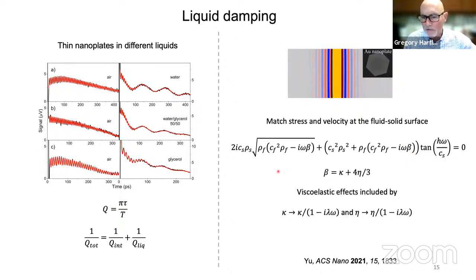Okay, so this equation has the densities of the solid, the densities and speeds of sound of the solid and the liquid. It has the viscosity of the liquid in this beta parameter. So if you leave out viscosity, then you just have the liquid like it was a solid. You can add viscosity by including beta, and you can add viscoelasticity, include the relaxation time, by modeling the viscosity of the liquid in this way. This is called a Maxwell model. This includes the relaxation time. So you put all this stuff in, and then you compare this to the experimental measurements to see if you can detect